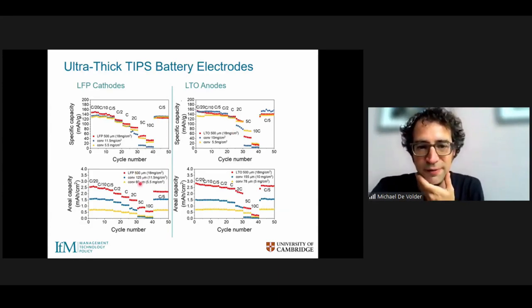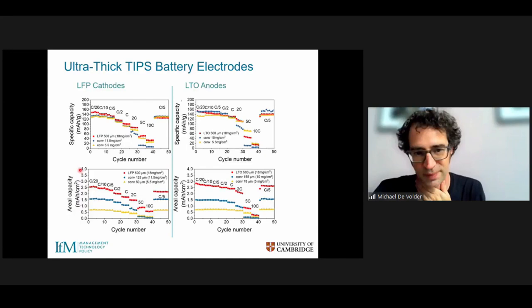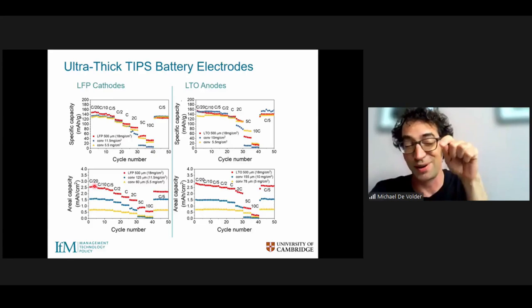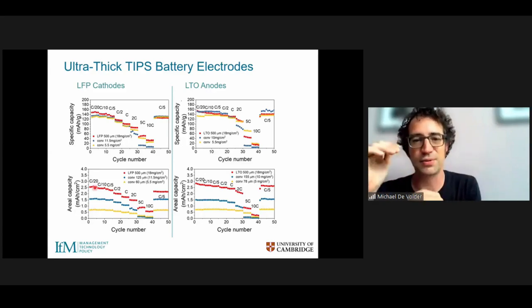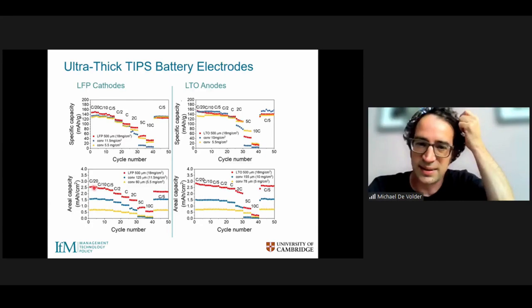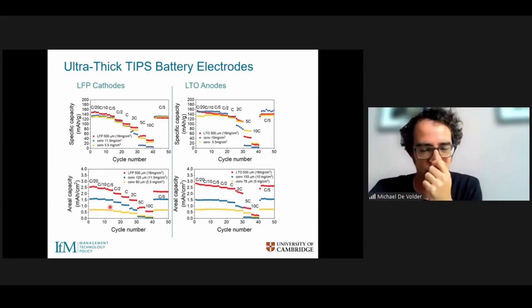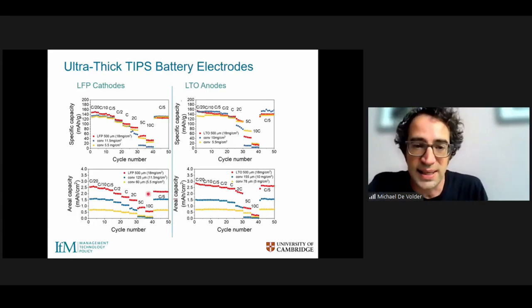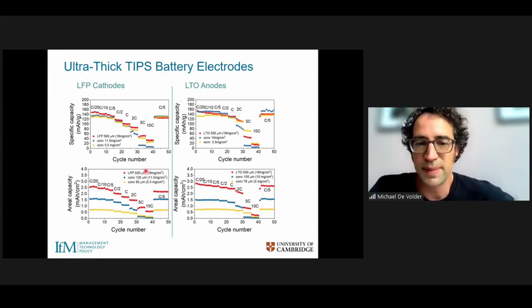We start with a conventional coating in yellow of 60 micrometers, and then this graph shows on the vertical axis how much lithium ions we can store per square centimeter of coating. And you can see that if we use the phase segregation process to make a very thick electrode, we can store much more energy than in a conventional battery. And that's true for both the anodes and cathodes. You can see, for instance, that by using a phase segregation process for a 500 micron thick electrode, we can about double the areal capacity compared to classic electrodes.